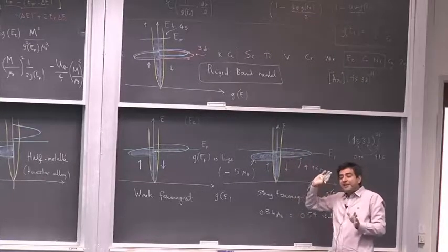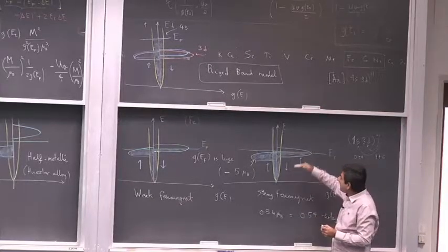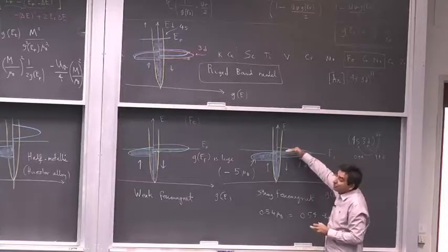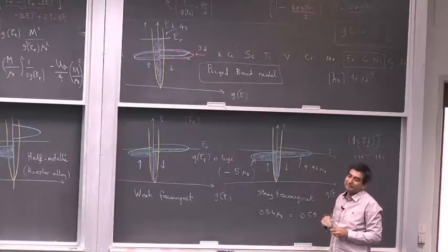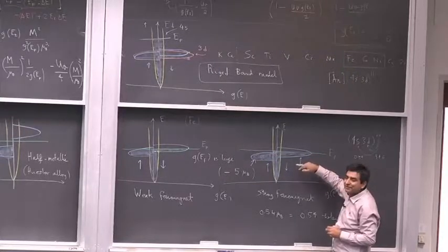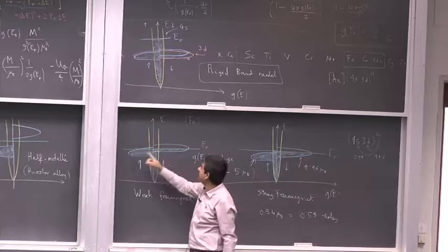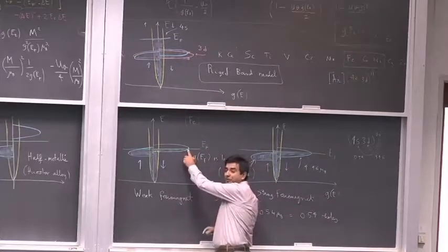So the magnetization of any material is intricately linked with the conduction properties, with the transport properties. The minority spin carriers play the most important role in conduction studies, because the Fermi level is intersecting with the minority band. Here it's intersecting with both, but the density of states for the minority band is larger at the Fermi level.